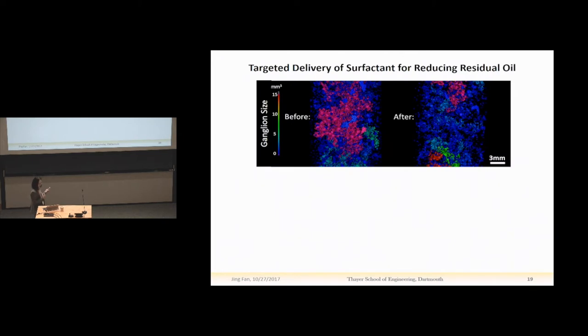And then we inject one pore volume of capsule suspension, and these capsules have surfactant encapsulated inside. And after the capsule flooding, we flood another five pore volumes of water to help the oil blobs move and flow out of the column. Then after that, we scan the column again, and this time we saw that much of the large oil blobs either disappear or are broken into small oil blobs like this.